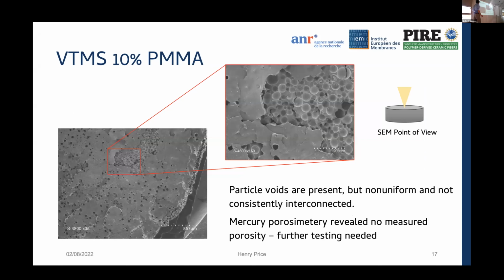Now, it's important to make note of one of the goals of the project, which was to use this PMMA to induce some porosity. So this is a really helpful image to show exactly what's happening on this micro scale. As you can see, this is a pyrolyzed sample. These are the pores, the vacancies caused by the removal of those PMMA beads.